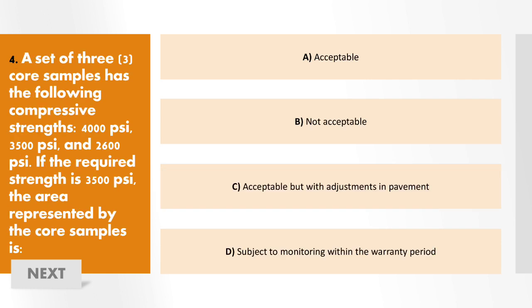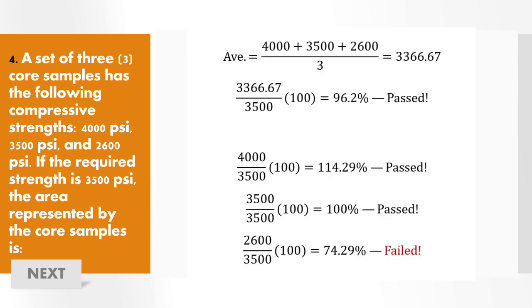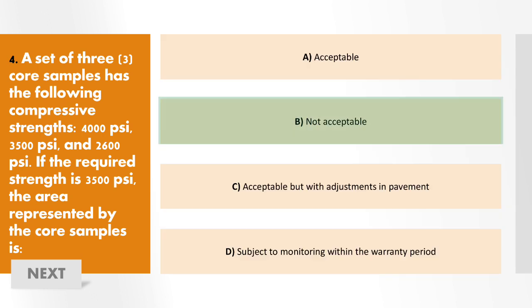Next, we need to determine if the area represented by the core samples is acceptable or not. To answer this problem, we need to check kung ang average strength ng core samples is at least 85% of the required. And also, each one of the core samples must be at least 75% of the required strength. Upon checking, we can see that the average strength of the 3 samples meets the 85% requirement. However, for individual checking, one of them did not meet the 75% requirement. In this case, the area represented by the core samples is not acceptable.